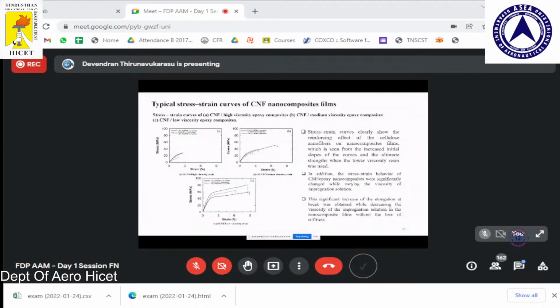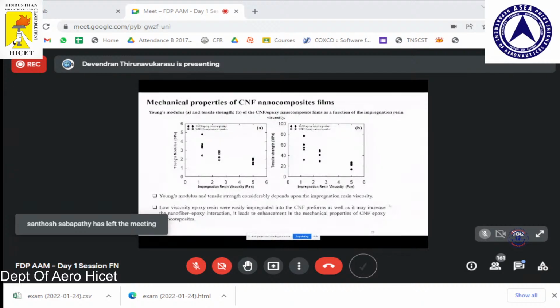The low viscosity resins have good mechanical properties compared with high viscosity resins, because impregnation with high viscosity resins is very difficult. The higher viscosity resin just sits on our film, but the lower viscosity resin is impregnated into our nanofilms. This is the Young's modulus for the different types of nanofibers we mentioned here.